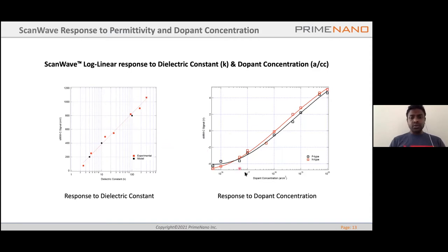This is also true when you look at the variation in the dopant concentration on the right, where I have the x-axis with the variation in the dopant concentration and the y-axis is the sMIM response. As you can see, here we have shown the variation of the dopant concentration between E15 to about E20. And you can see the response is almost linear in all of the range. There is a slight variation in the slope at the lower end of it. It's just because of the intrinsic capacitance variation at these dopant concentrations. But as the variation is monotonic, it helps in identifying the characteristics of an unknown device.